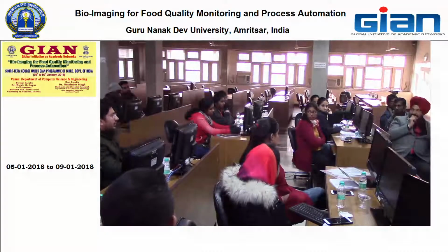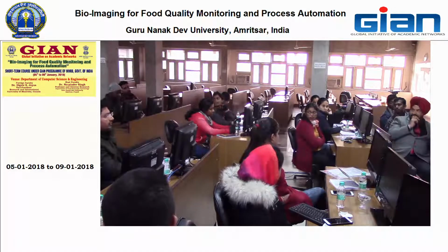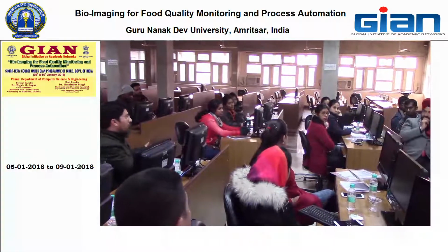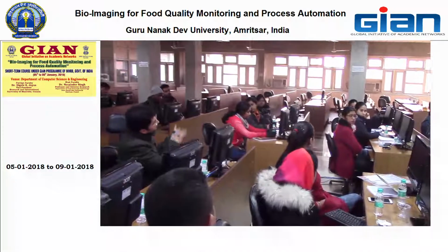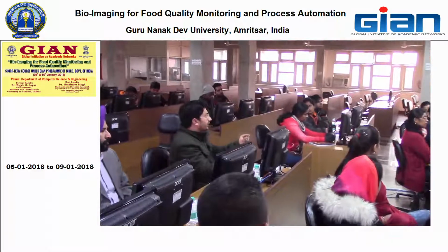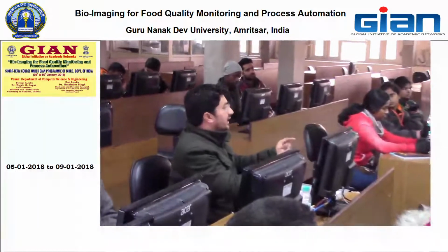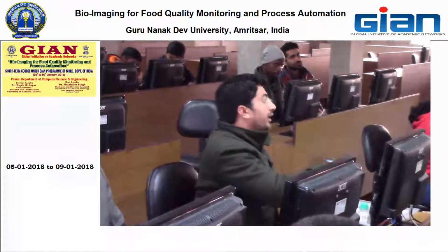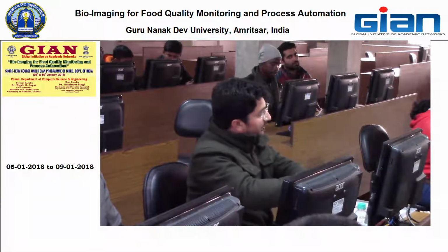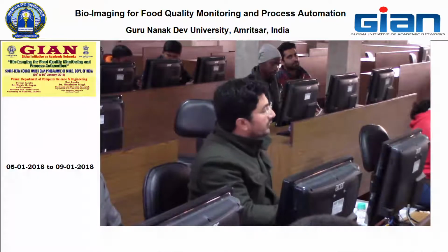What I am understanding is you have some images not from an electron microscope, maybe from a simple compound microscope. You can analyze those images also. But for the size, you have to standardize using the classical method of ocular and stage micrometer. And using that calibration in the software, you can do it very easily.